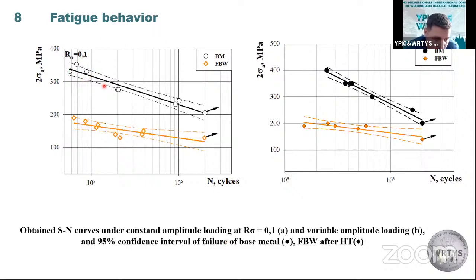Here you can see the obtained S-N curves for constant amplitude loading at stress ratio 0.1. The endurance limit at 2 million cycles is 200 MPa, and flash butt welds give us near 130. That gives us near 60% of the base metal. Specimens tested at variable amplitude loading give us near the same results, near 200 MPa and 150 MPa at base 2 million cycles.